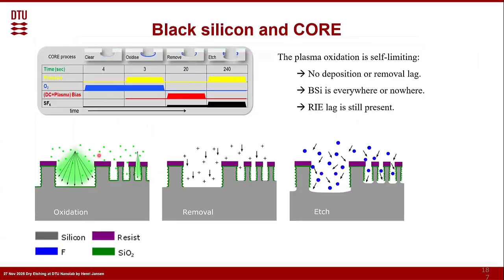So what are the consequences? If you now look at the plasma oxidation, there is no deposition or removal lag, because the oxidation process is of course much faster. After half a second it's already there, but after 1 second it doesn't go further that much anymore, whereas this one is still gaining. So after maybe 2 seconds they're already identical, and then you can continue, but there's no big difference. And then you continue again with the bottom removal step, but now because they have the same thickness, they are removed in the same way.